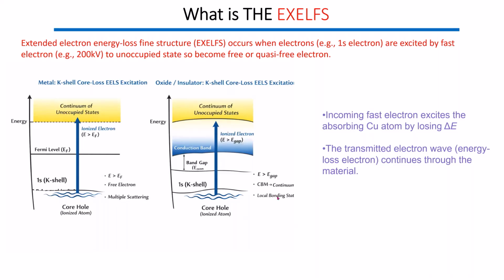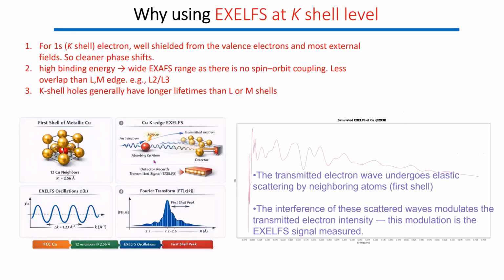So how this extended fine structure happens is that, as we said, the electron is being excited to the unoccupied state. In that sense, let's say for copper, it will lose roughly 8,900 electron volts, and then you will get transmitted electrons, which undergo elastic scattering by neighborhood atoms. That's where we see this oscillation or interference you see over there. So that's where this modulation of the signal you've seen here comes from, and here is the simulation result.